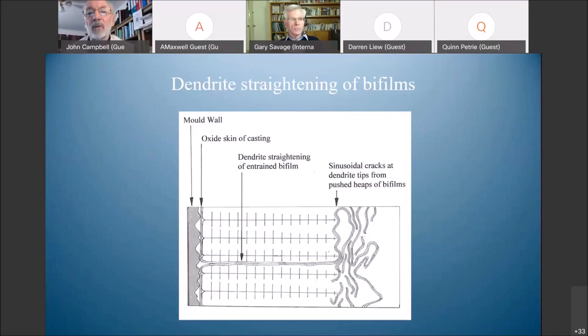And this is one of the mechanisms which happens with bifilms. I don't know whether you can see my cursor, but as the dendrites grow, they tease out and elongate and straighten bifilms, and they push ahead. The remnant of this great heap here is being pushed. But this straightened bifilm now becomes a straight crack, like an engineering crack, and so becomes really extremely important in terms of properties.